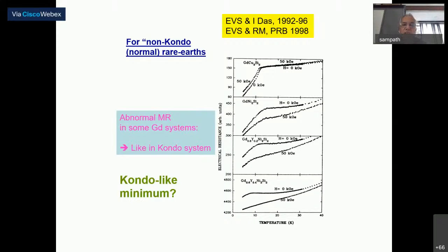Now, what we found, in some of the materials which we were studying in 1996, is that instead of seeing this behavior, we found there is a significant magnetoresistance in some of the materials. I listed some of them here, and there is a significant change in the electrical resistance as a function of field, and this raises a question to us whether there is any extra contribution coming up here. So, in other words, subtract the lattice part, you see a Kondo-like minimum here, but it doesn't go logarithmically in the system. Then we thought, okay, why not study more compounds and try to see.